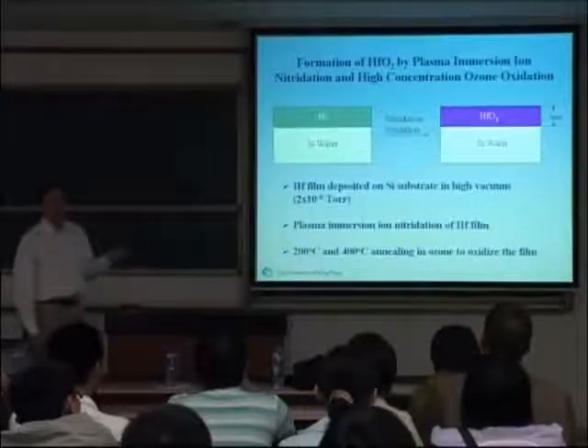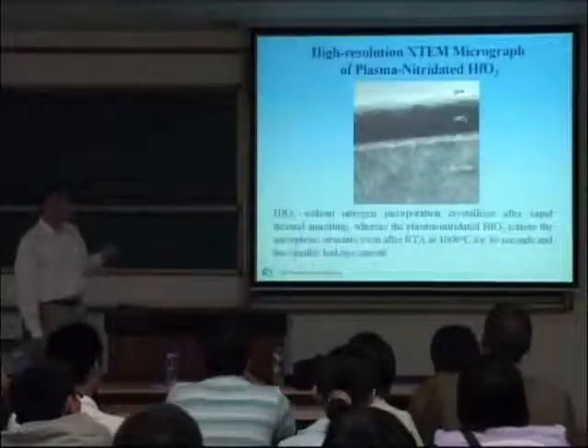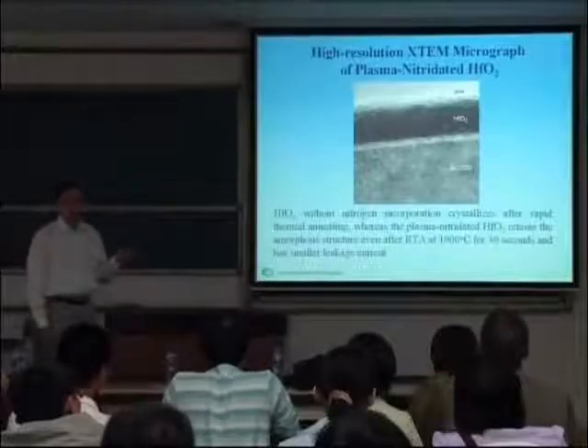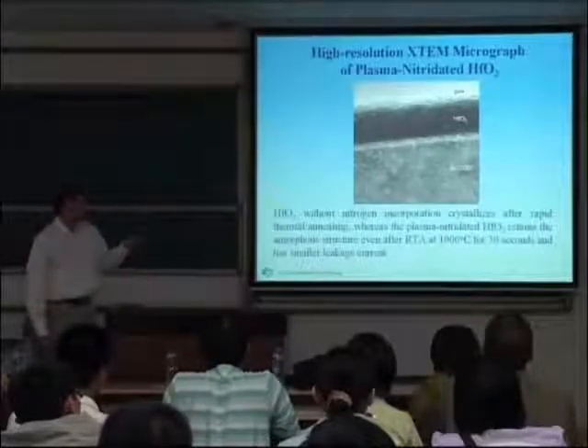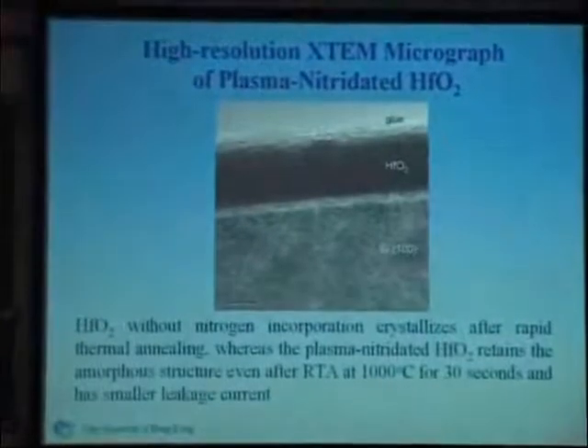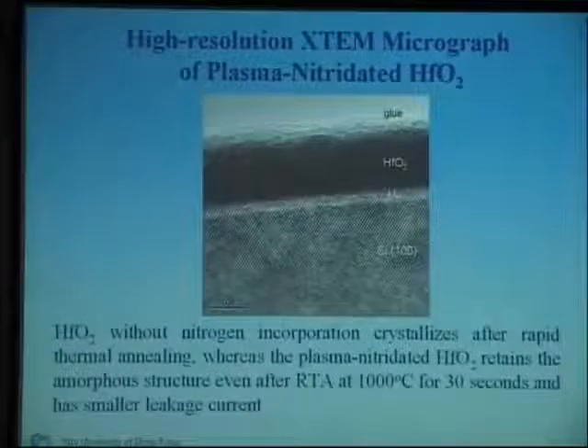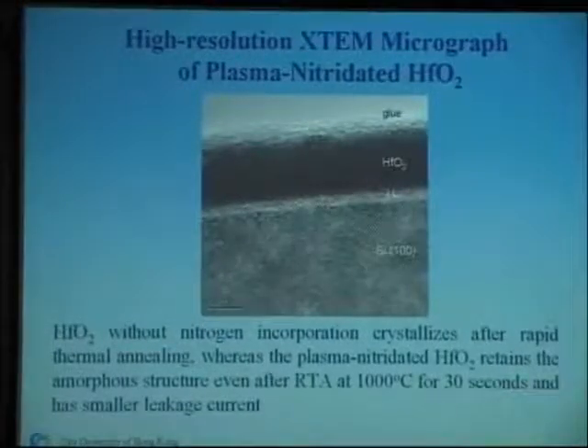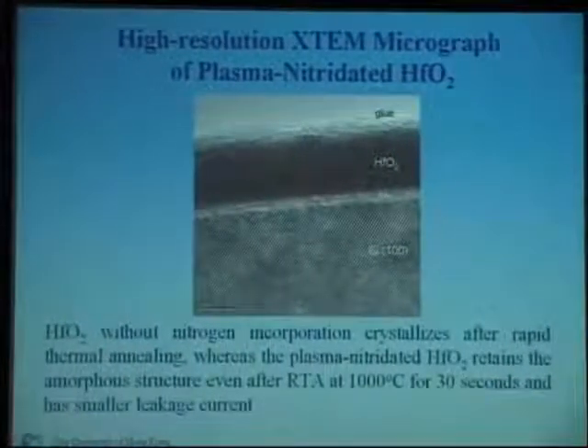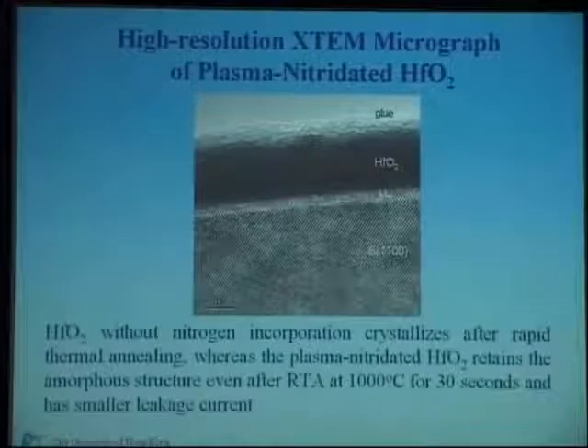I'm going to show you just one picture to give you some idea how good that is. This is a high-resolution transmission electron microscopy picture. This is a silicon substrate. You can see each atom — each one is one silicon atom, right here. Single crystal, each one. This is hafnium oxide, amorphous. So we have been successful in making that. Science works — we can use the technology to build something so nice.